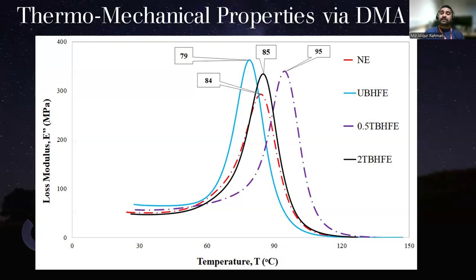When we incorporated the treated fiber, the maximum we can see is for the 0.5 hour treated fiber with the epoxy, which is 95 degrees centigrade, an incredible advancement. However, for 2 hours, it dropped again, probably because, as we found earlier, some of the crystalline cellulose was taken out.